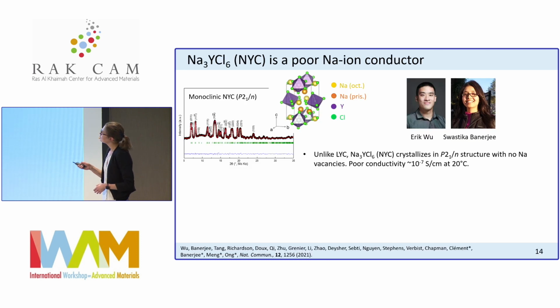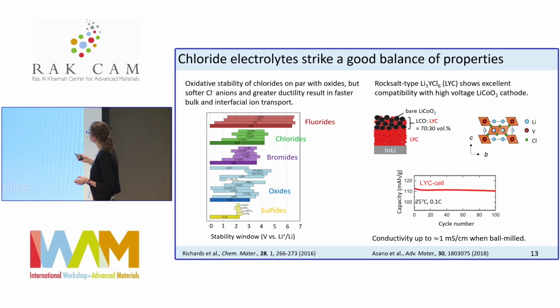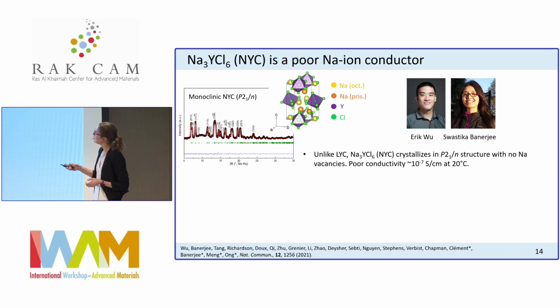So we decided to explore the sodium version of this material, sodium yttrium chloride, or NYC. This is work in collaboration with 2 groups at UC San Diego, the group of Shirley Meng and the group of Shyue Ping Ong. Eric here synthesized this NYC material, and what we found was that instead of making the same crystal structure as LYC, which is a rock salt-like structure with a P-3m1 space group, in our case we're making a monoclinic